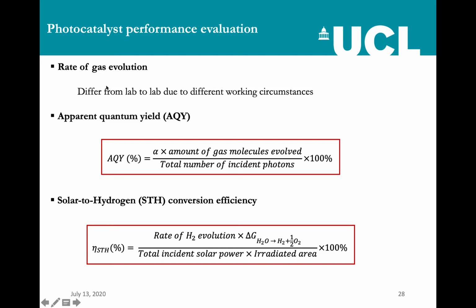And these two, apparent quantum yield and solar to hydrogen conversion efficiency, are the highly accurate or reliable forms of measuring the efficiency, because the rate of gas evolution can be varied depending on the different circumstances in each laboratory. One probably uses a very high power solar energy lamp like a xenon lamp or any other lamp, and some people use a lower energy lamp, some people use monochromatic radiation. So there is a lot of confusion.